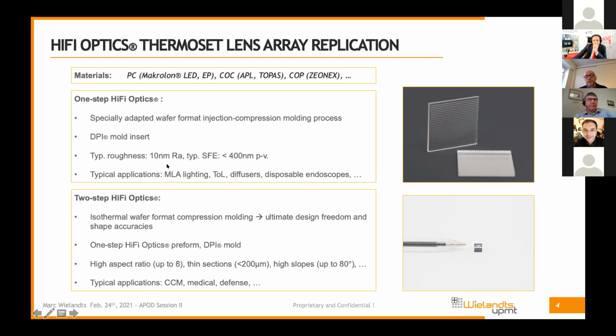and of course the process is adapted to the structures every time. When the quality that comes out of the 1-step process is not sufficient, there are limits, of course, to injection molding. If you go to extremely thin lenses, then the process ideally becomes a compression molding process, and that is what we call the 2-step hi-fi optics process. It allows us to make very small CCM stacks, self-aligned, because the optical surface and the alignment surfaces are molded together, micron accurately aligned.